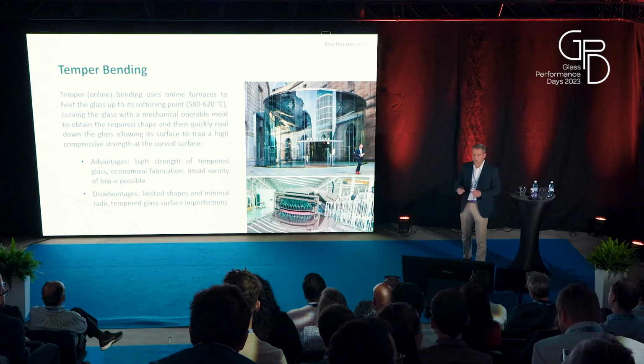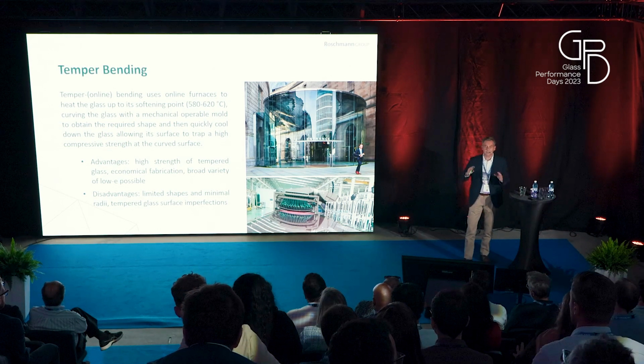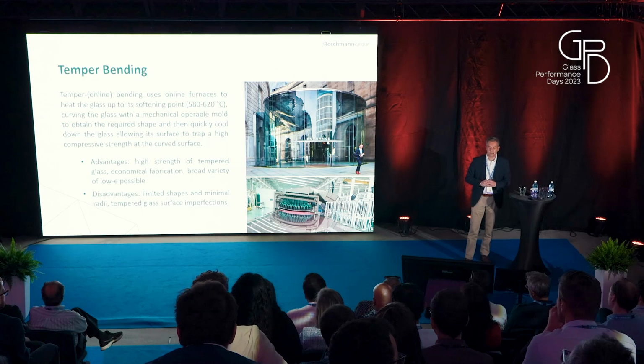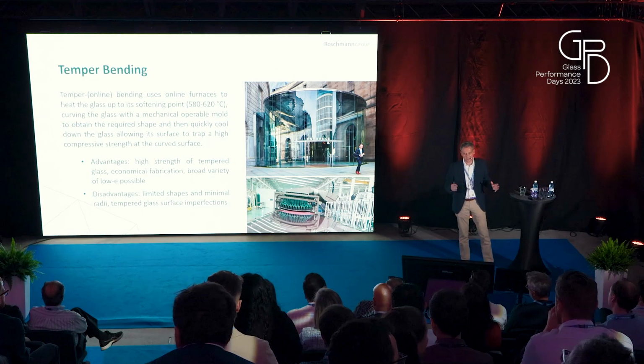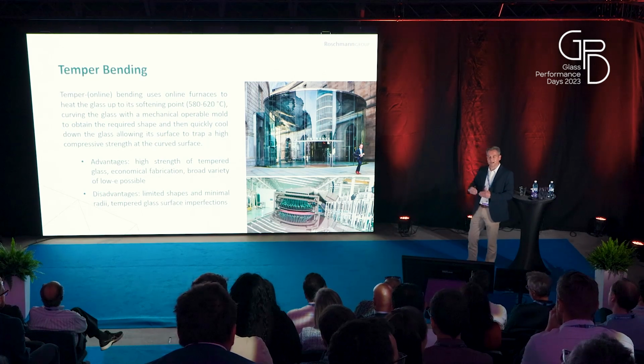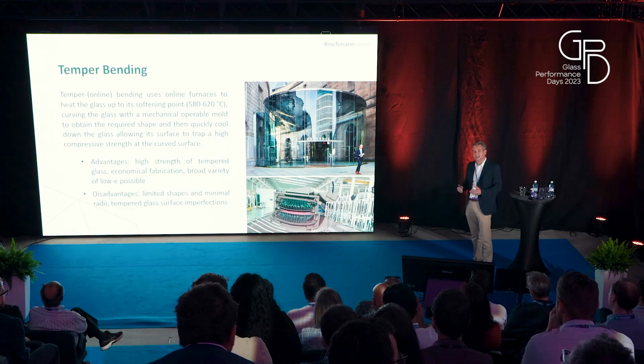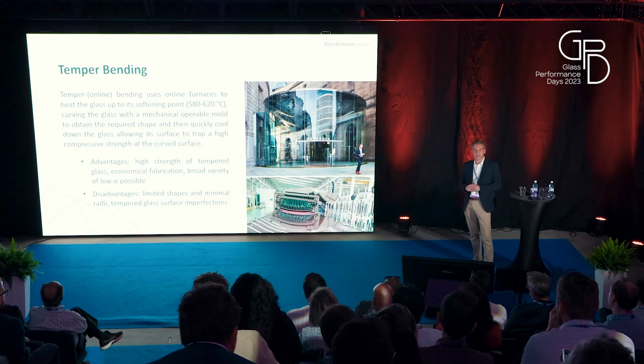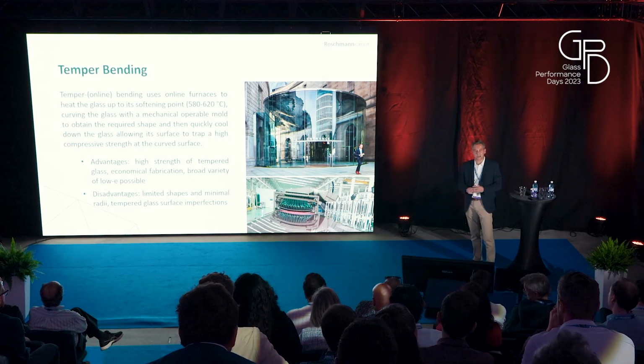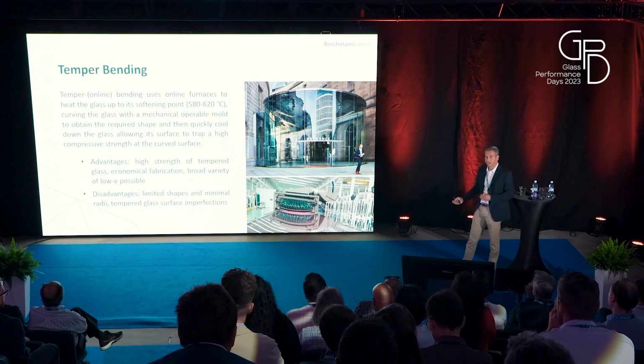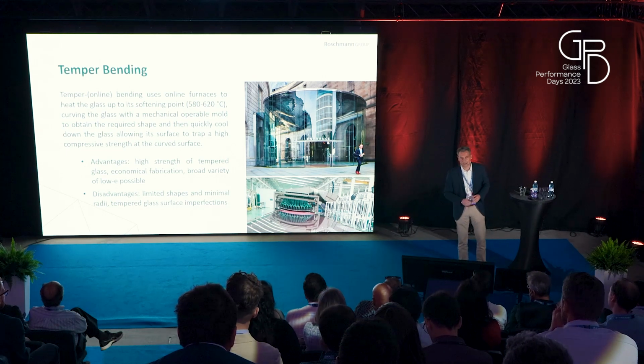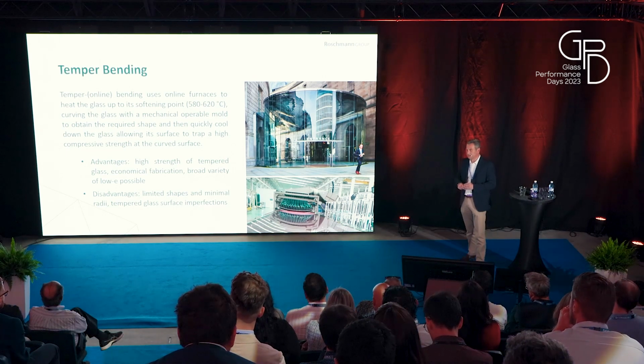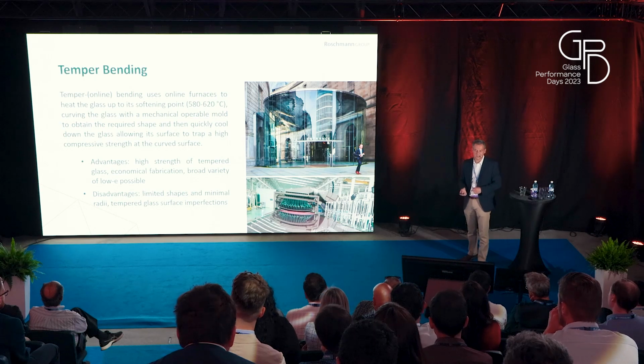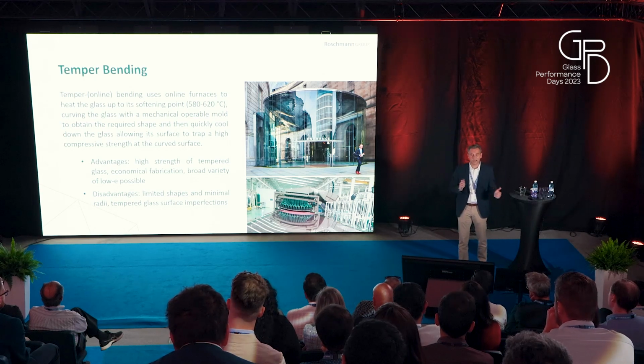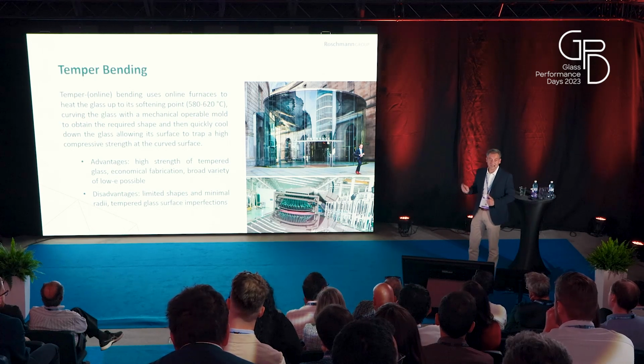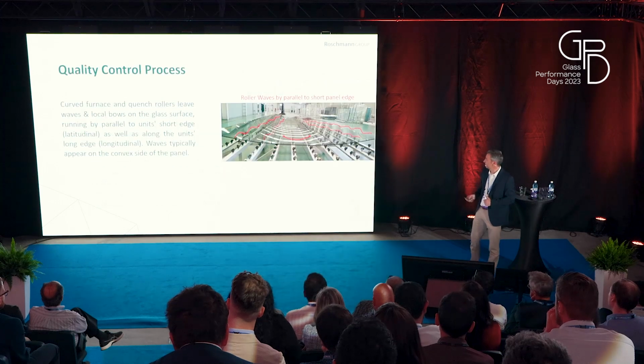So the architect wanted to have a clear and crisp surface without any distraction. The only problem with temper bent glass is that I am facing distortions which may appear on the glass surface, which are roller waves and local bows, which may create a kind of distortion on the glass. So that's the only problem I do have with tempered glass. But it can be managed, basically.